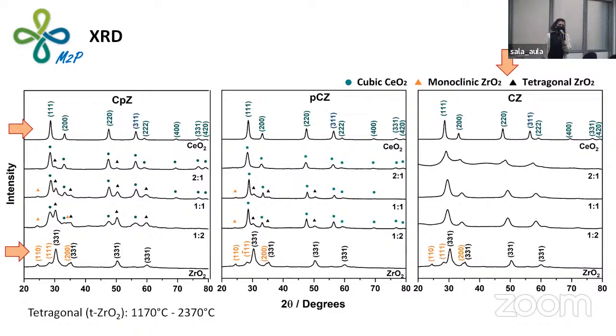Starting to show the results, first we have the XRDs. These are the diffractograms of CPZ, PCZ, and CZ. And we can see that, as expected, ceria was crystallized in cubic phase, while zirconia was crystallized in monoclinic and tetragonal phase. I believe that we were able to get tetragonal phase because we used the microwave system, because it allows us to reach metastable phases at smaller temperatures.